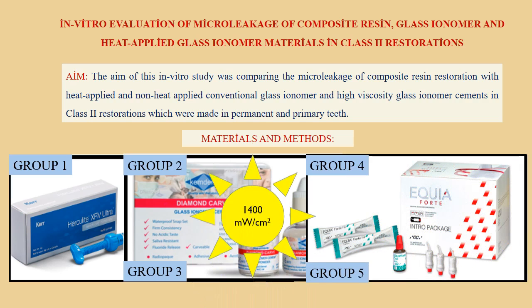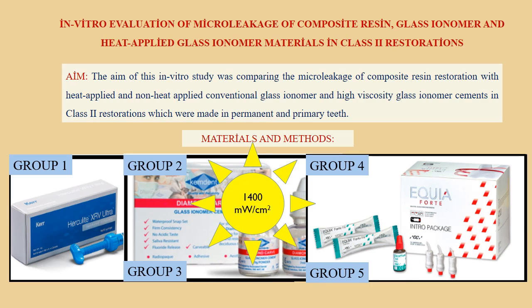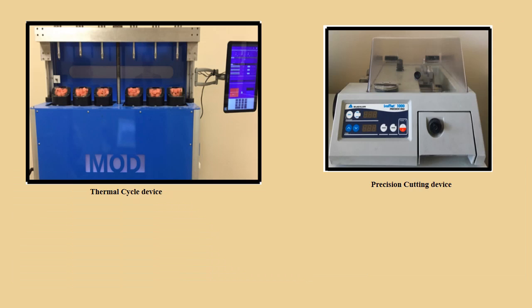While Groups 2 and 4 were applied heat in high power mode with the D-Light Pro LED light device. Groups 3 and 5 stayed as the non-heat-applied groups. Samples were aged under thermal cycling.